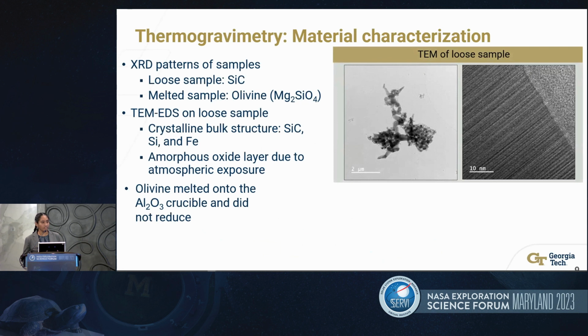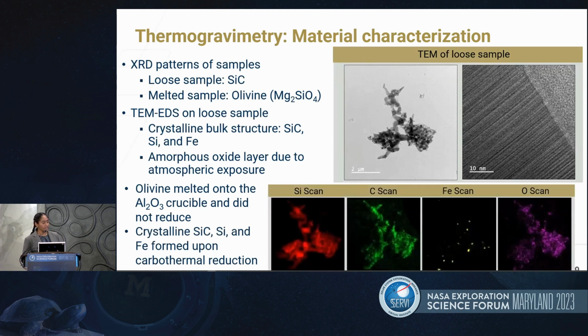So TEM results show that the sample was crystalline with an amorphous surface layer. And with EDS, we confirmed that the crystal is indeed silicon carbide, with the silicon scan and the carbon scan coinciding with one another. EDS also showed that pure silicon and pure iron were formed, but in small quantities.